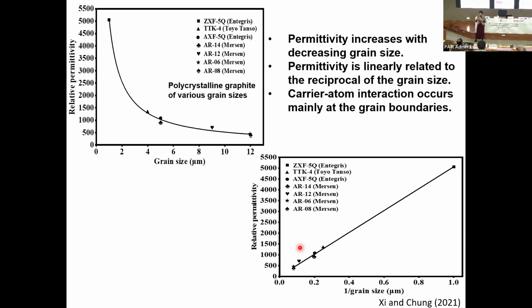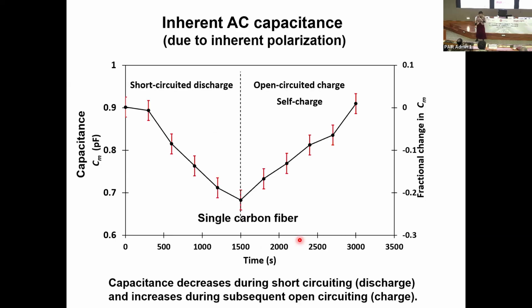To look at the effect of grain boundaries, we also looked at graphites of various grain sizes. And we find that as you decrease the grain size, the relative permittivity increases greatly. And if we plot the relative permittivity versus 1 over grain size, it's more or less linear, indicating that the carrier-atom interaction occurs mainly at the grain boundaries.